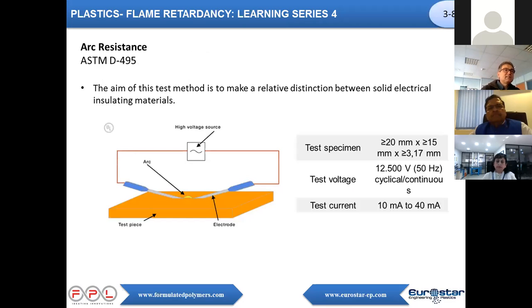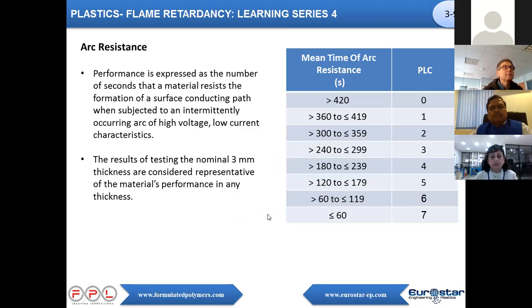The arc resistance is another test. It's very similar in principle to the CTI, but in this case, the voltage is very high. So this method is intended to differentiate in a preliminary fashion among similar materials with respect to their resistance to the action of a high voltage, low current arc close to the surface of an insulation, tending to form a conductive path, causing the material to become conductive. So this time, the electrode is not moving, it is fixed, but you have a high voltage applied to the system, and you are measuring the time to arcing. So it's expressed in seconds, meaning that the voltage is varying automatically, and you're measuring the time to formation of a conductive path.